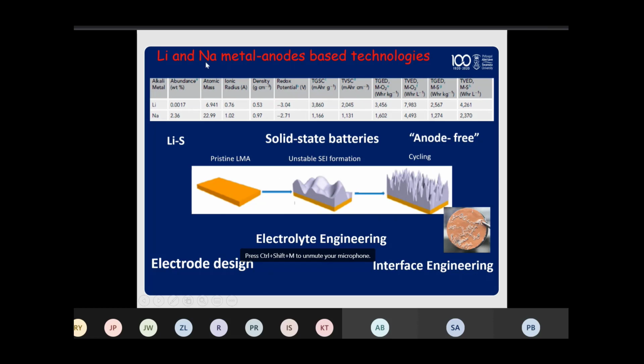The problem of enabling such anodes is all down again to what I told you at the beginning in the discussion of the SEI formation. The SEI that is formed at the first cycle is really unstable. It's not homogeneous, and it breaks and reforms constantly. And therefore what we have upon cycling is the formation of dendrites. So the lithium metal develops in this fashion, as you can see on this slide. This is my own formation of dendritic sodium on a copper. And this is the major cause of battery degradation, and the reason why such technologies are not yet there in terms of cycle life.